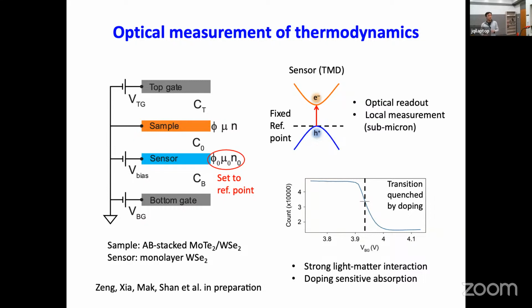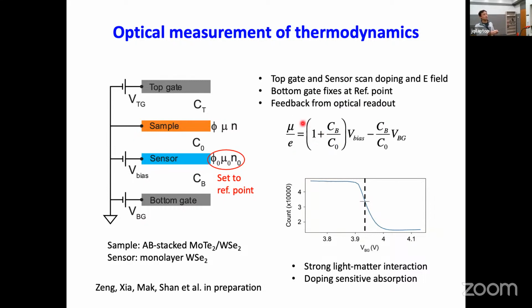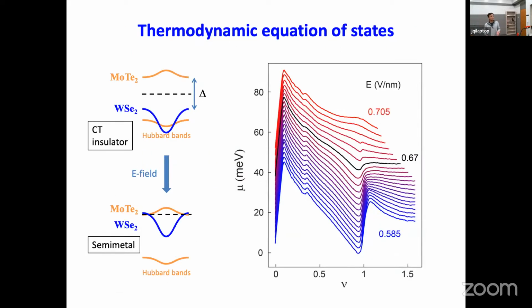So in our real experiment, we use our sensor and the top gate as two gates to tune the filling and the electric field in the sample. The bottom gate is just to keep the sensor at this fixed point through a feedback loop from the optical readout. Then we can directly read out the chemical potential in the system. And as a local probe, we can easily do chemical potential imaging as well. I will show you an example.